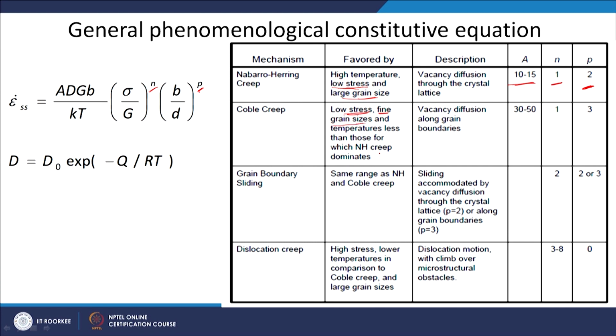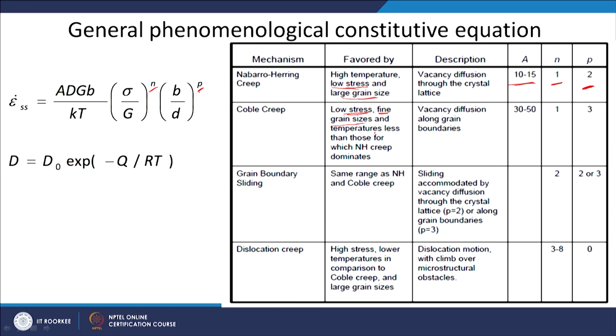For Coble creep, again it is at low stress but in fine grain size, at temperatures less than those for which Nabarro-Herring creep dominates. So it happens at lower temperature. Why does it happen at lower temperature? Because grain boundary diffusion will be faster, because grain boundaries already have an open structure. So diffusion of atoms through the grain boundary can take place at lower temperature also, whereas diffusion through the lattice requires vacancies, and you can have higher vacancy concentration only at high temperature. So Coble creep can dominate for fine grain size as well as for lower temperature.